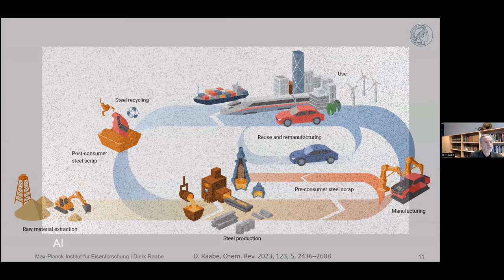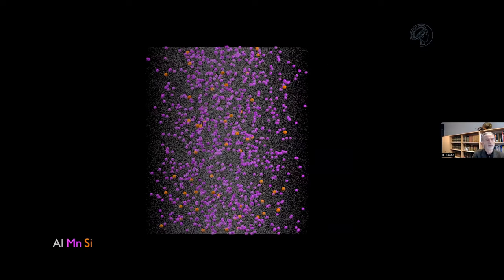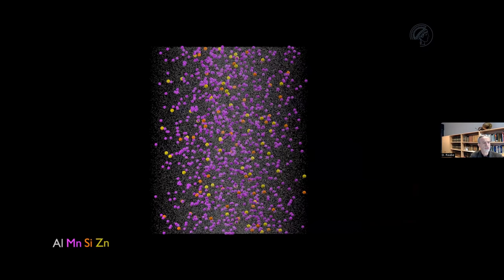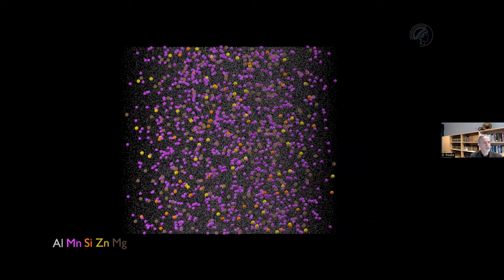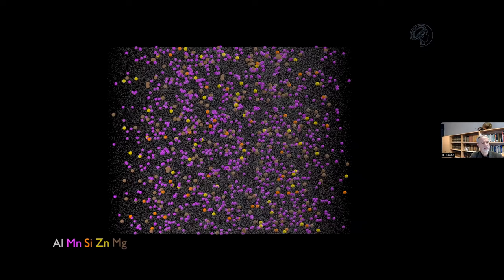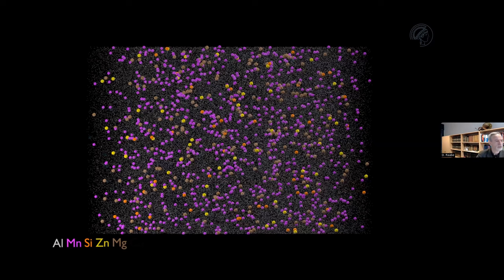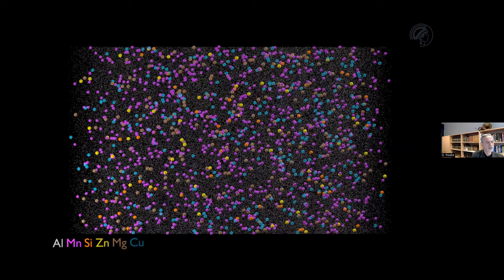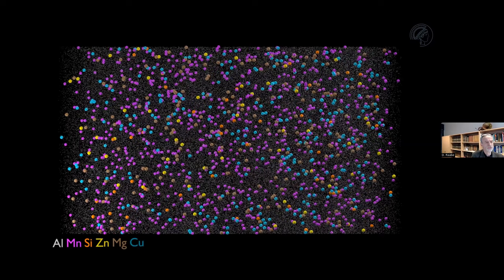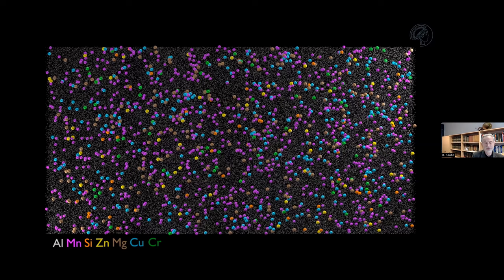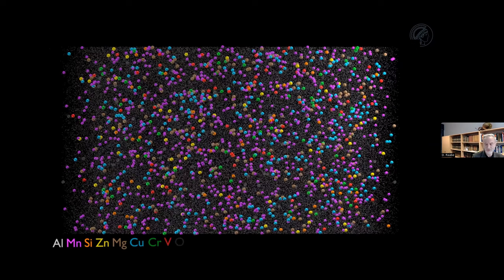A second aspect is shown now not for steel, but for aluminum, but the principle is the same, in this movie. This is an atom probe tomographic experiment where the single dots indicate the different atoms that you would find, for instance, in the drinking can. When you drink a soft drink and analyze the material, it should be essentially relatively pure aluminum with a little bit of manganese. But you find up to 15 different elements nowadays in packaging aluminum, which all comes from the included scrap, from the mixed material that you get from post-consumer scrap.